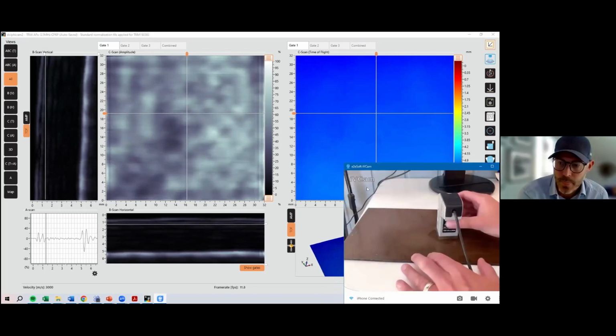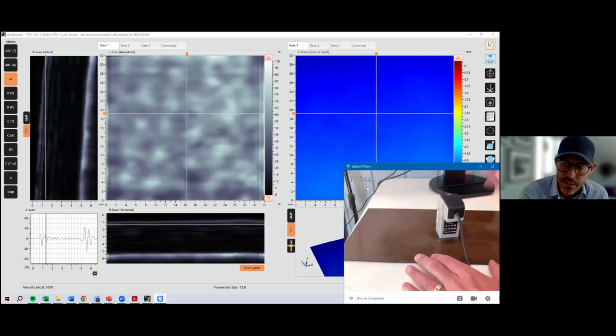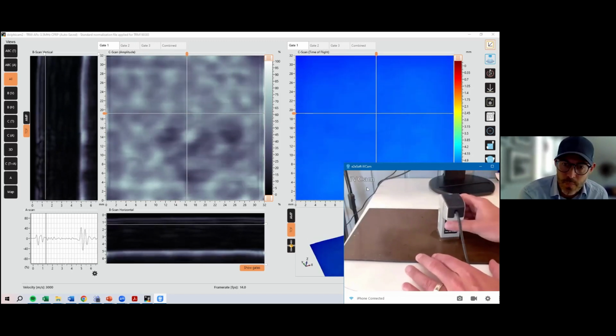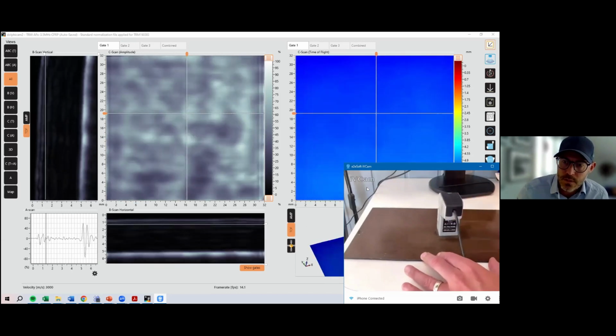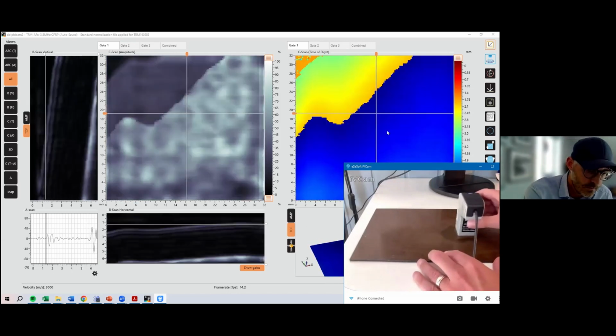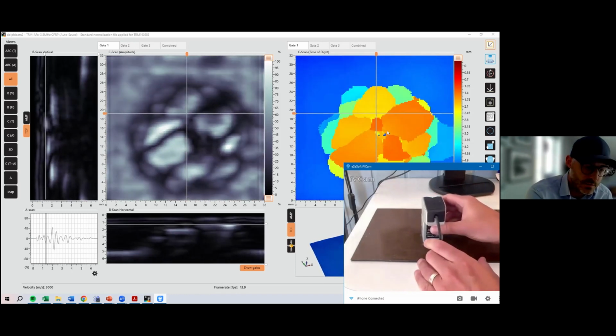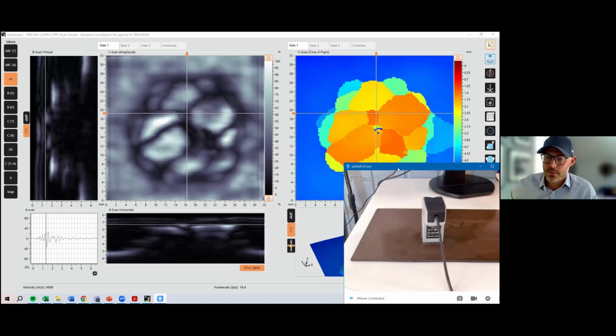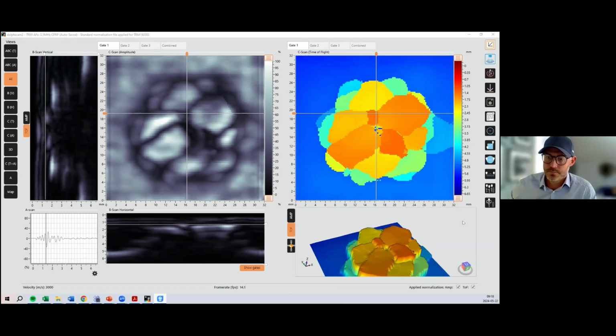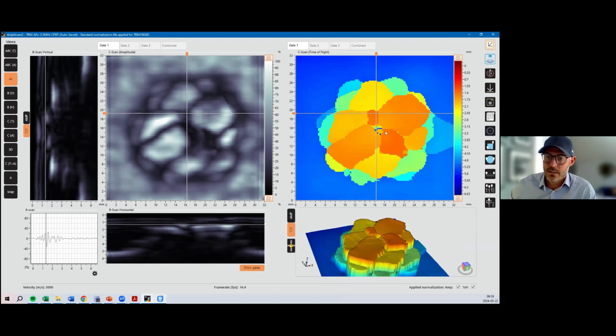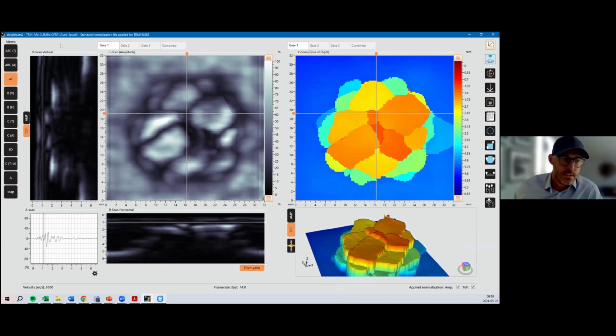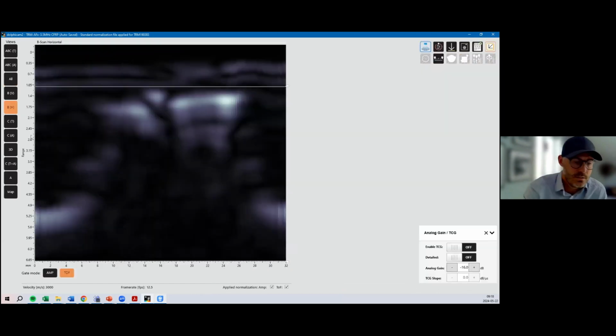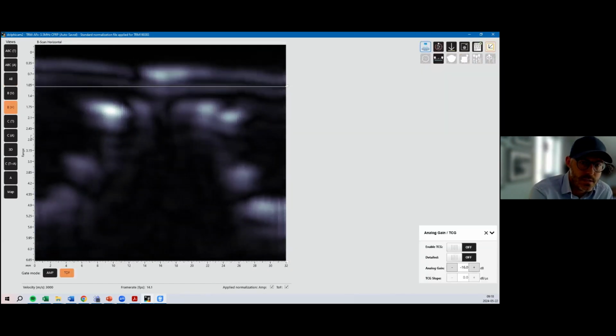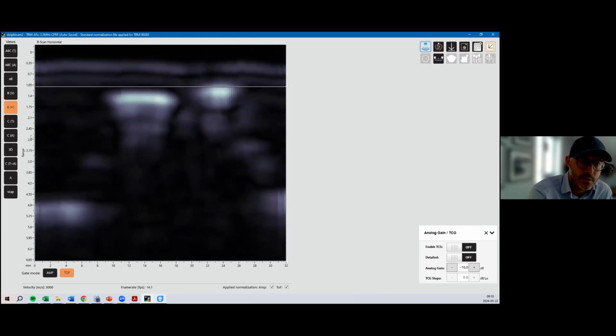But imagine that you have set this up at United Airlines or another aircraft, and you say, if this picture here is blue, then everything is okay. But if I move it over to a damage, like here, if you get colors in your image, then you have a damage. So you can see this one here, both in 3D, C-scan time of flight, and also amplitude, right? So imagine just having the B-scan to look at, which is okay. It gives you quite a bit of information compared to the A-scan.